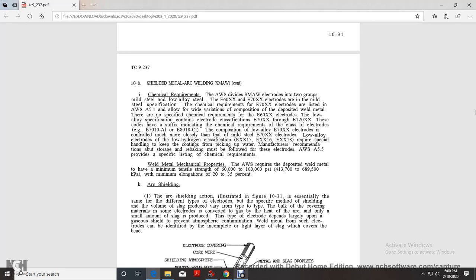The low hydrogen low alloy electrodes, classifications EXX15, EXX16, and EXX18, require special handling to keep the coating from picking up water. Follow the manufacturer's recommendations for storage and rebaking. Rebaking must be done with these electrodes. AWS A5.5 provides a specific listing of the chemical requirements.